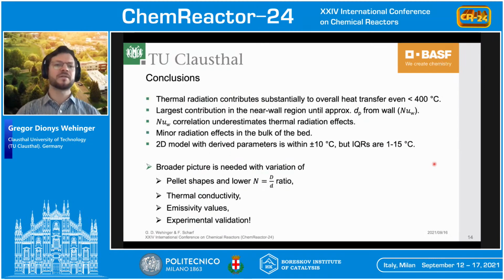So let me conclude my talk. I showed you in a theoretical study that thermal radiation contributes substantially to the overall heat transfer in packed beds, even below 400 centigrade, where we typically do not expect that. The largest contribution in this scenario, hot wall cold fluid, is in the near wall region until approximately 1 particle diameter away from the wall, which is then represented by this Nusselt wall rather than the K effective radial. However, the typical correlation of Nusselt wall rather underestimates the thermal radiation effects.